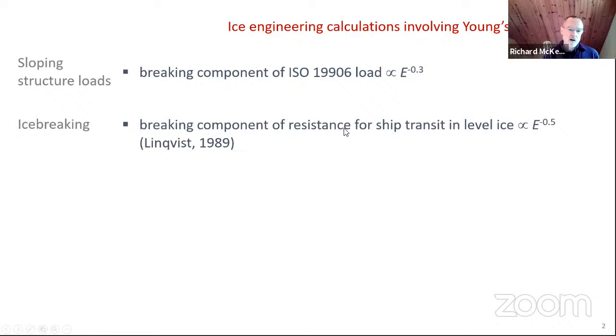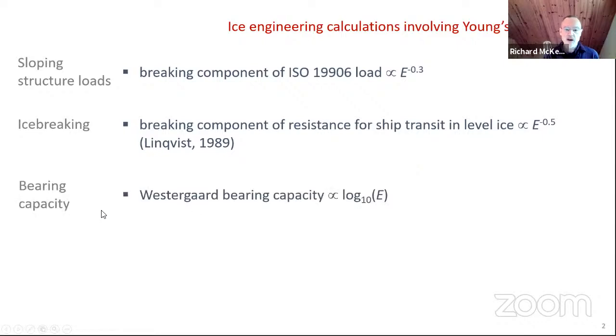In the ice-breaking component for ship resistance, the load is proportional to E to the minus 0.5, so it's a little bit stronger effect. In a bearing capacity equation, also in the ISO standard, the bearing capacity is a function of log E.